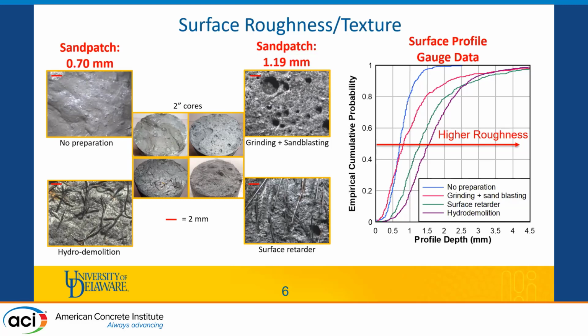0.70 millimeters. Now, moving forward to the grinding and sandblasting, it clearly looks more rough than the no preparation, with an average result of the sand patch of 1.2 millimeters approximately. And the graph on the empirical cumulative probability of the profile gauge results shows more roughness because the graph is more inclined towards the right.